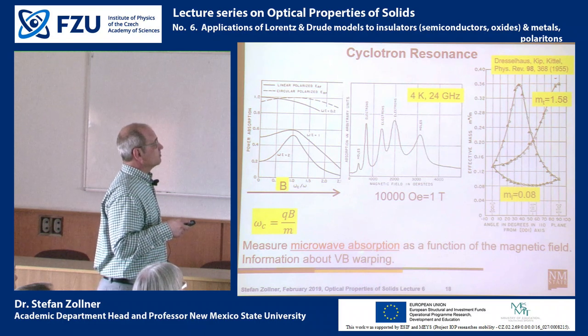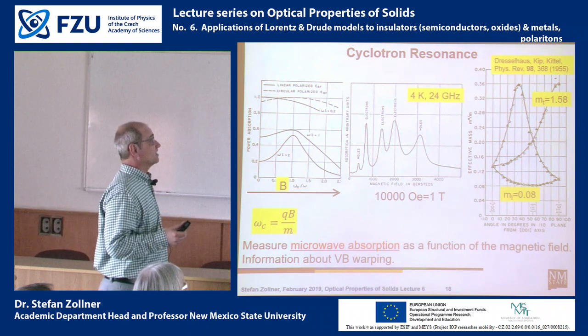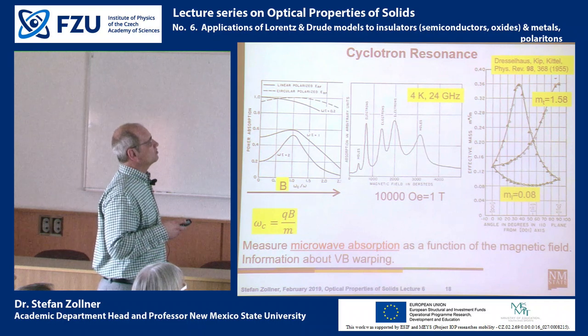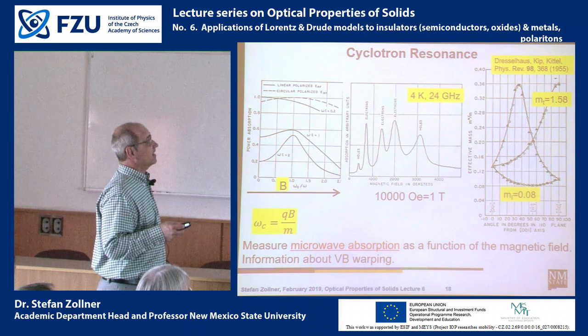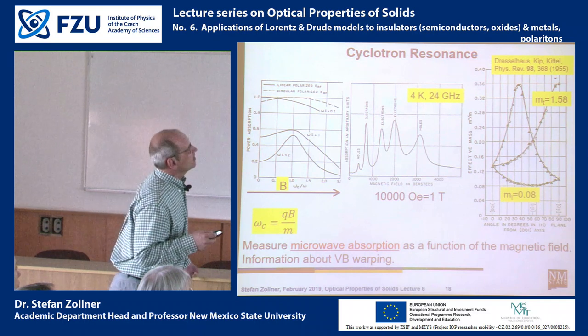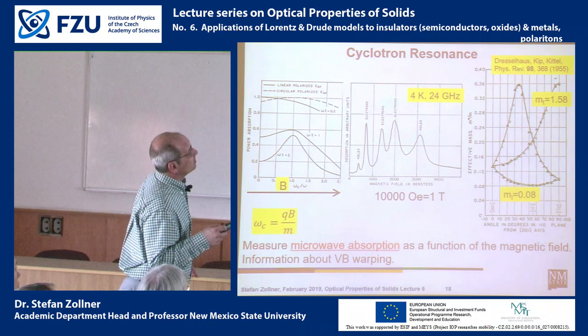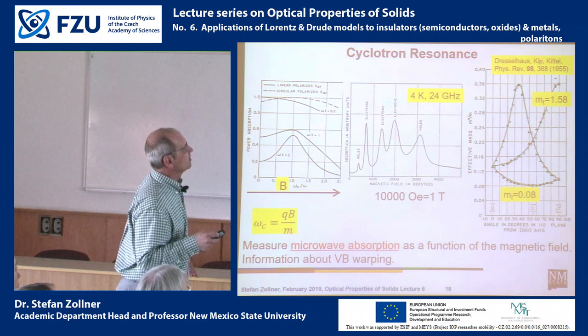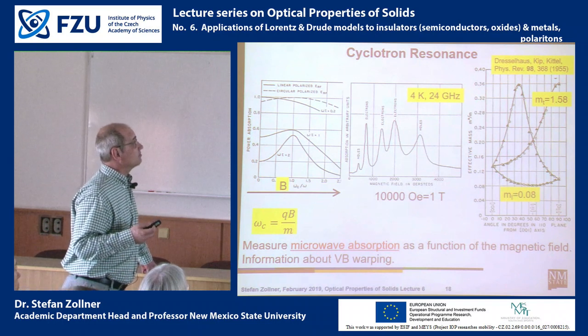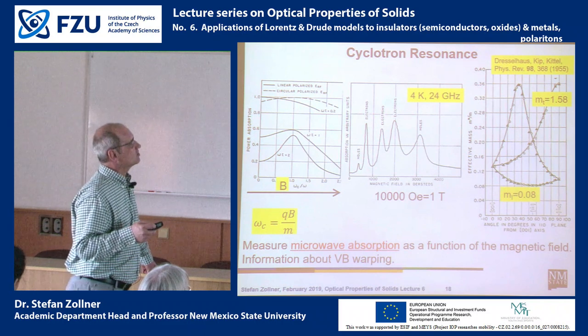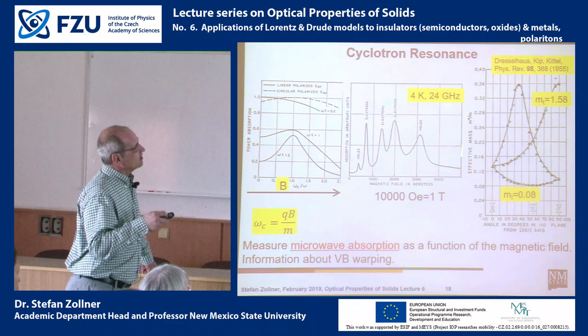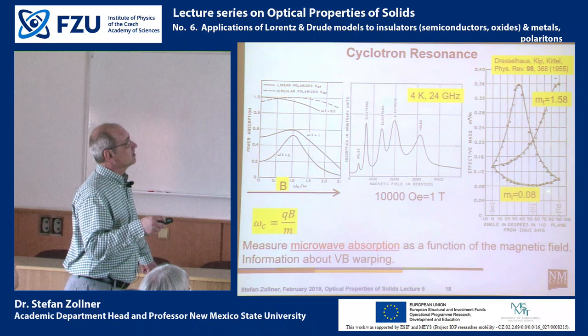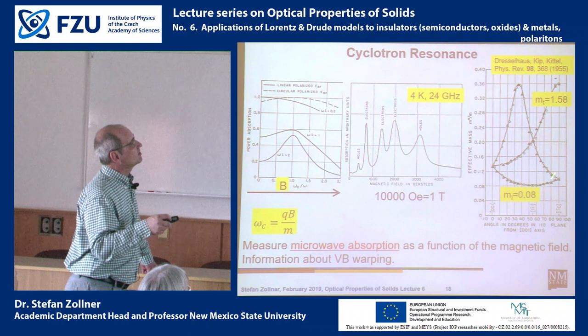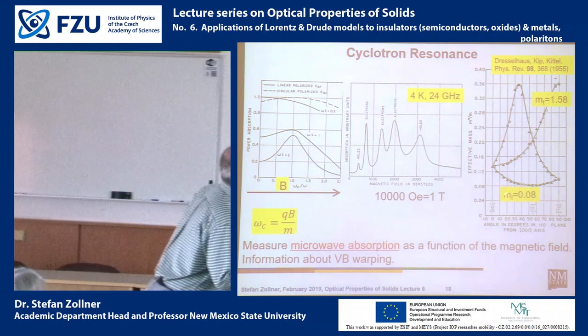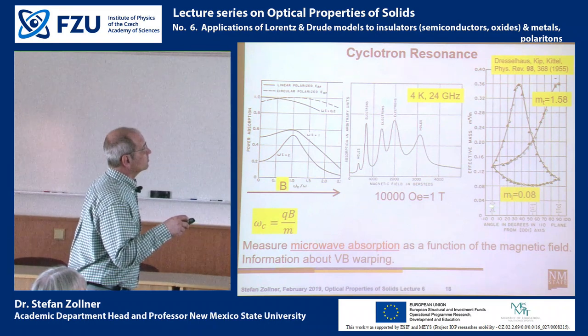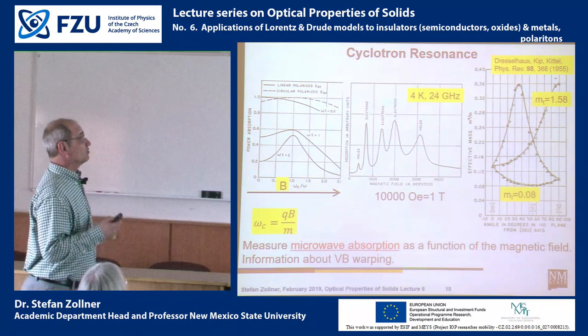Then by changing the direction of the magnetic field relative to the sample, you can map out the effective mass tensor with the components in the various directions. The famous paper here that needs to be mentioned is Dresselhaus, Kip, and Kittel, which goes back to 1955. By performing microwave absorption measurements in a magnetic field with different directions, here we are plotting the effective mass as a function of the direction of the magnetic field, it is possible to extract the longitudinal mass, and I'm sorry, this is the transverse mass. It is possible to map out the transverse mass and the longitudinal mass for germanium or for other semiconductors.